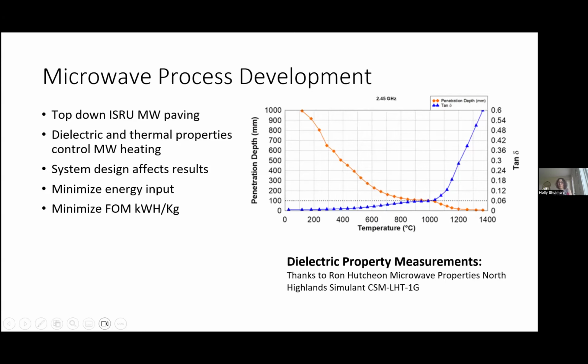So a radiant heat source is super important to give the kickstart heating, but you don't have to heat that whole volume. You just need surface heating, because then that will re-radiate inward and you'll be driving that microwave energy inward. So just with anything, the practical view of it, when you're firing ceramics and you're heating them from the outside in, just a conventional way, it's radiant heat. It has to move in. You have to heat extremely slowly, because ceramics usually have a very high heat capacity. It takes a lot of energy to raise its temperature, and it usually has very low thermal conductivity. So you just have to gently baby it along.